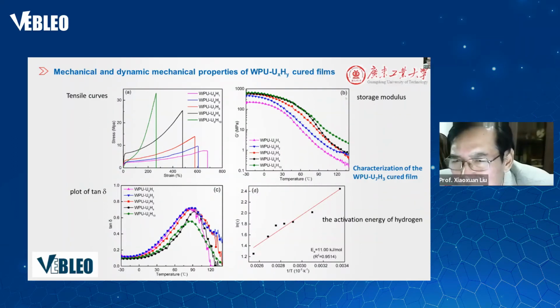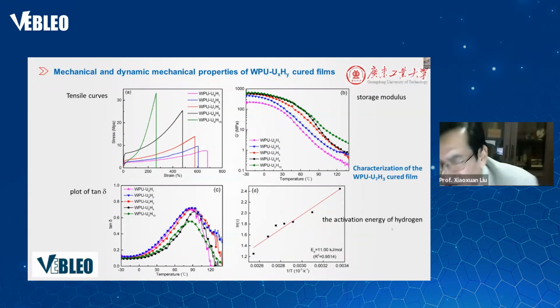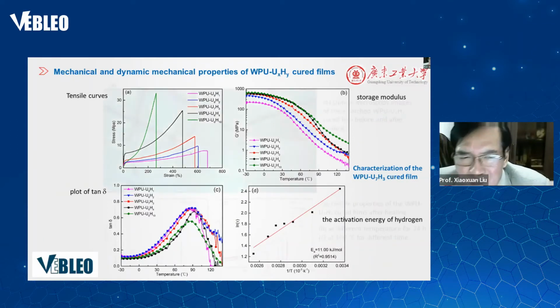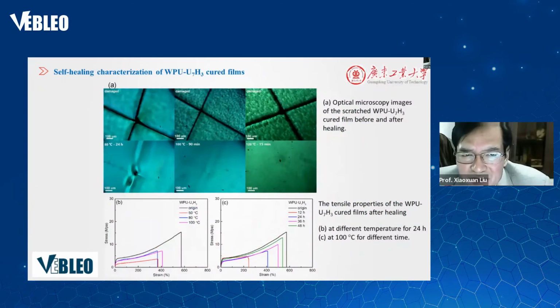And this is the curves of the storage modulus, which changes slightly. This is the tan delta, and the activation energies of the hydrogen bonds. So we can see the activation energies of the hydrogen bonds increase slightly. These are the characterizations of the WPU film.